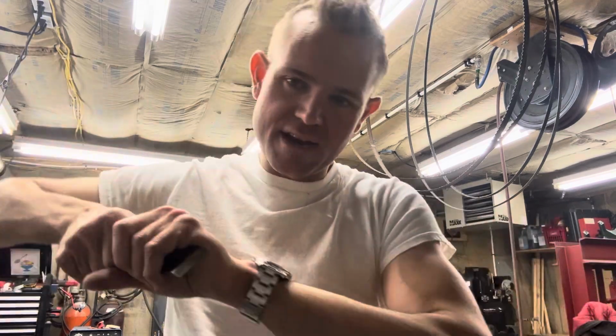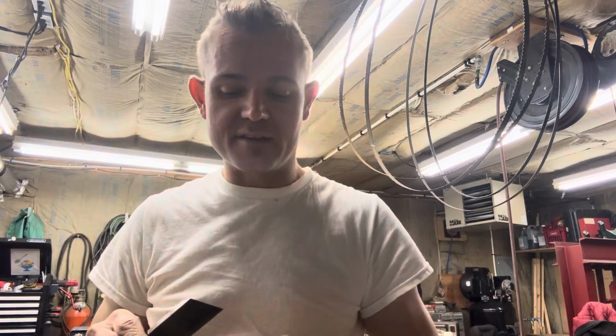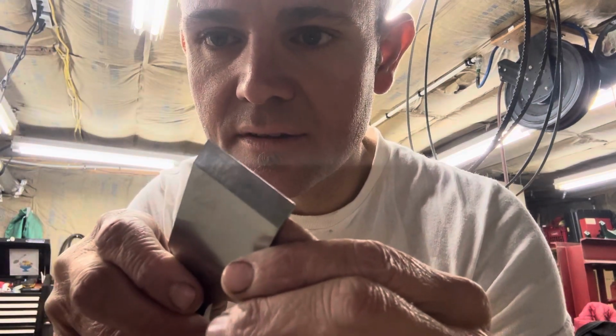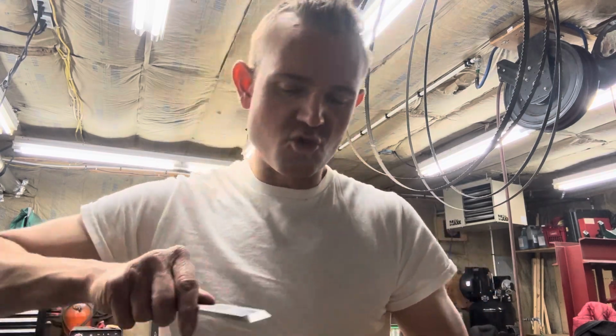This is a woodworking tool. You can use this just exactly as you would a chisel. No problem. How I do my edge retention testing is I put a chunk of aluminum in my bench, and I cut into it and cut shavings of aluminum out of it, and just take chunks and twist it, because if a blade's going to break, it's going to break there. I did probably 100 or so cuts and twists with this edge. You can still see aluminum deposits on it from the test, because aluminum rubs off onto the blade, and this thing still shaves hair just like it was. Nothing changed. I also took some Osage orange and was gouging at it and beating on it, and it appears to be unused still in terms of performance.